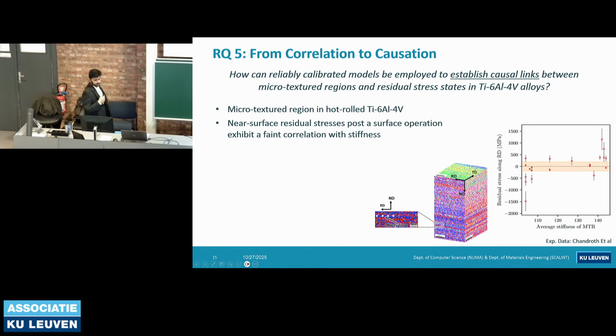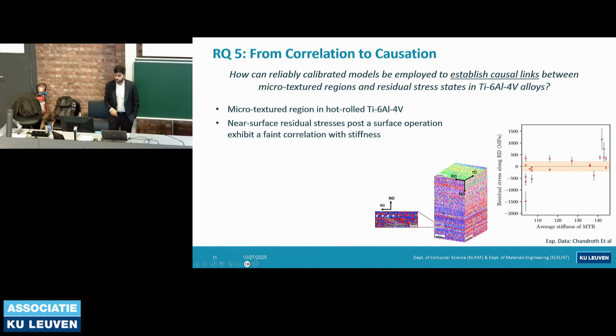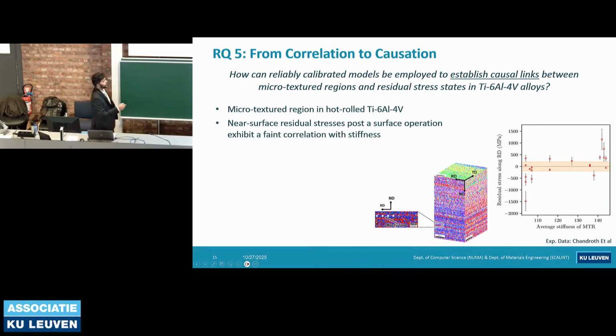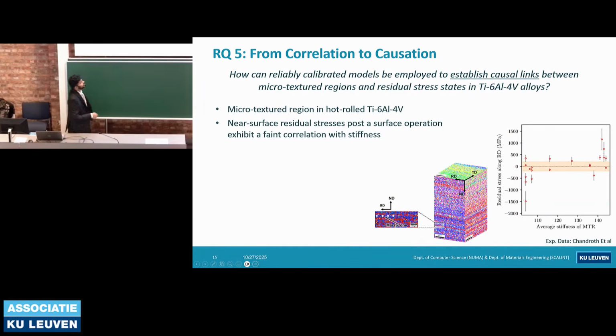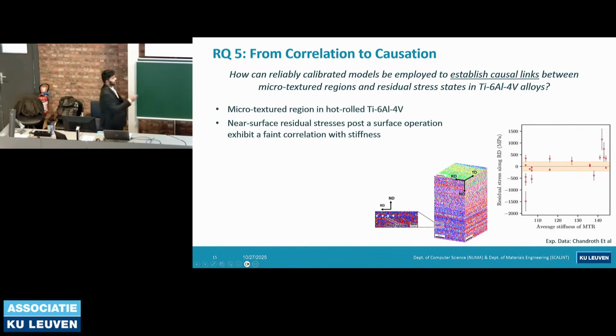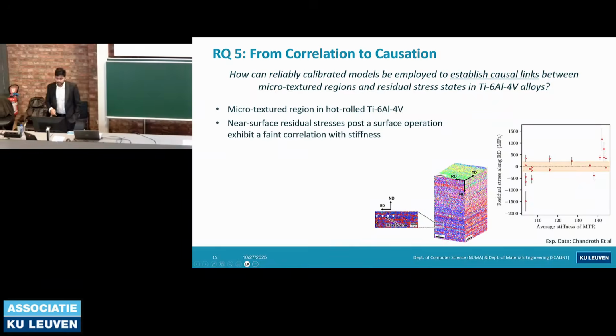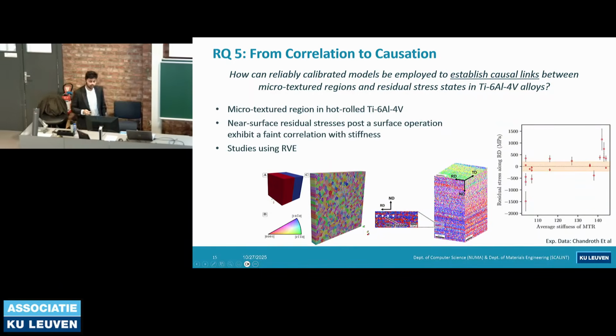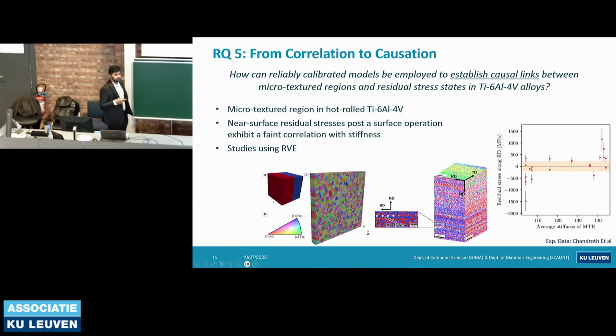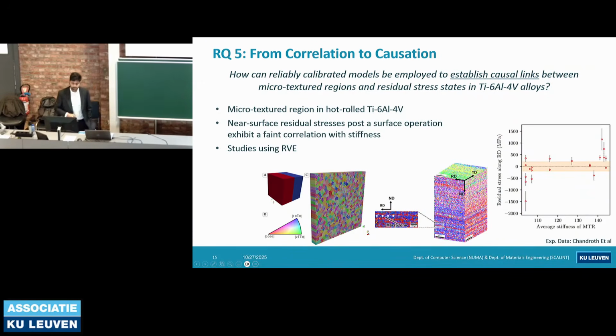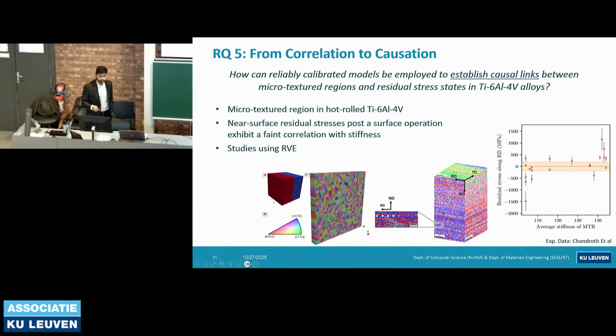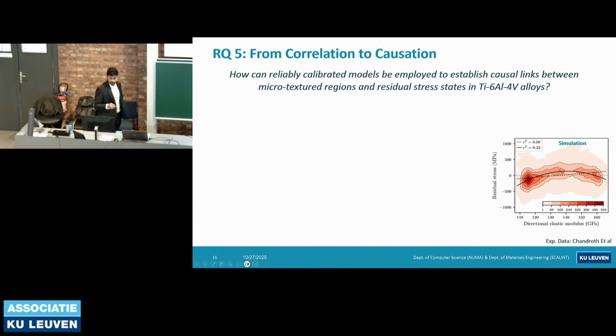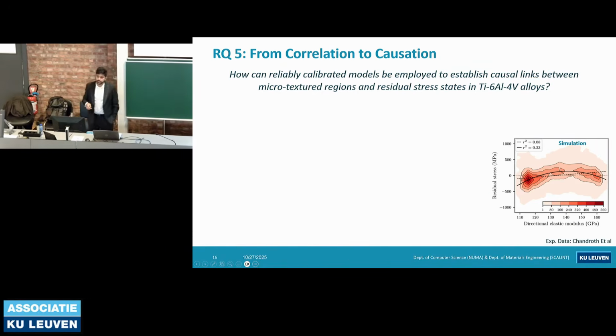It was seen that after a machining operation, the residual stresses generated had a hint of correlation with the stiffness of these zones. As you could see here, we cannot statistically say anything about this, but it gives us a hint that there might be a correlation between the stiffness and the residual stresses. For this, we used the reliable parameters that were identified from the last research question to study with the help of simple RVEs that you could see here. And from the simulation, we were able to reproduce the correlation that was seen in the experiment.